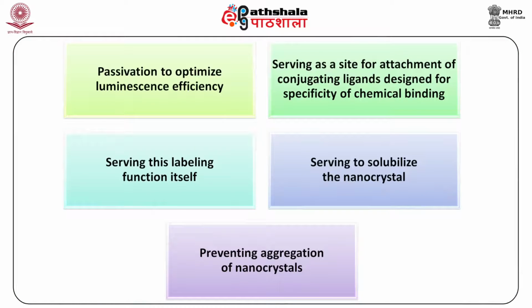They are typically encapsulated with zinc sulfide, silica, or an organic material. This capping is sometimes referred to as derivatization or functionalization, especially when an organic compound is involved, which is sometimes also referred to as the surfactant. The encapsulation amounts to covering the nanocrystal with a layer of material that may serve a variety of functions. For example, passivation to optimize luminescence efficiency, serving as a site for attachment of conjugating ligands designed for specificity of chemical binding, serving this labeling function itself, and serving to solubilize the nanocrystal and prevent aggregation of the nanocrystals.